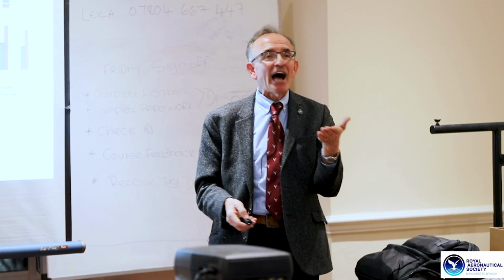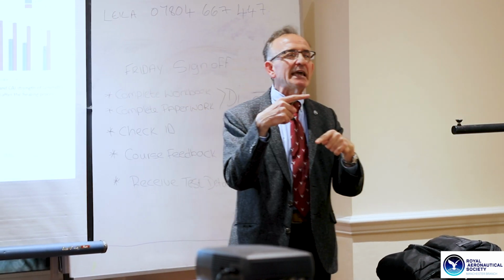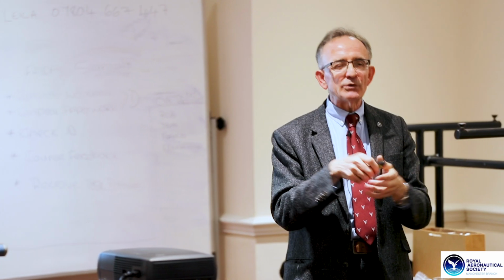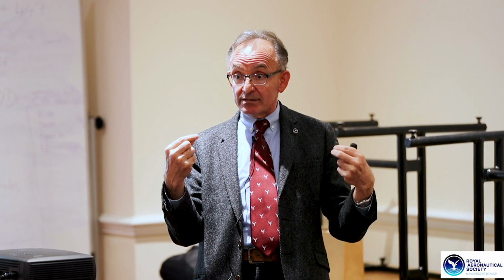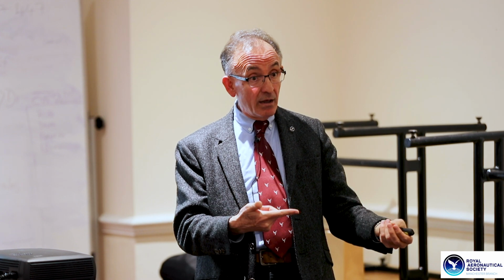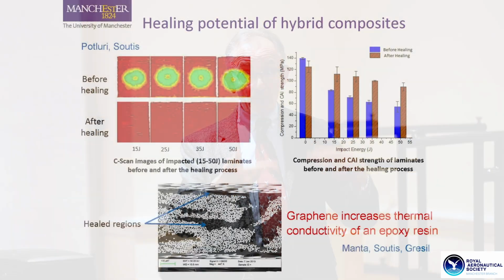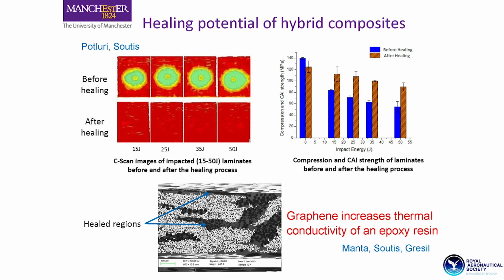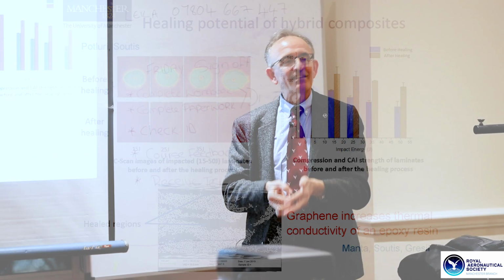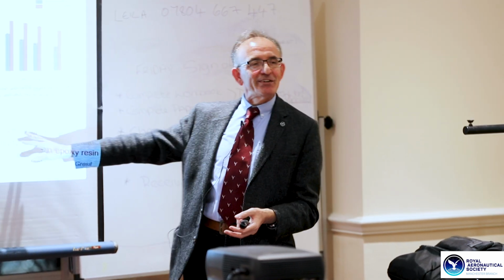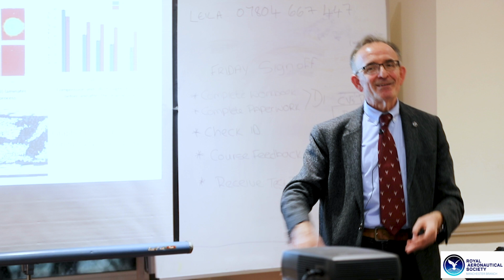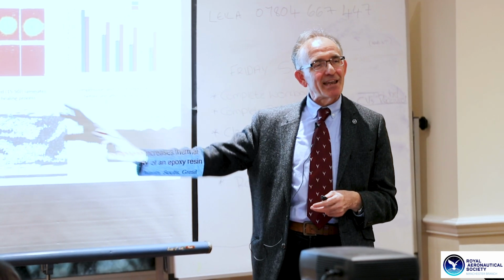And to one of those applications now, we can go back. You remember when we did the hybridization at the fiber level, where we used the thermoplastic fibers to protect the brittle glass fibers, and they give us the high strength and the high stiffness. And we said by heating up the material, the thermoplastic fibers will melt and will fill up the cracks. But if your polymer is not thermally conductive, you expose it to very high temperatures, so you might cause damage. But if your polymer is modified with graphene, which improves the thermal conductivity, it becomes much easier, and at lower temperatures, to melt those thermoplastic fibers and repair your composite structure.